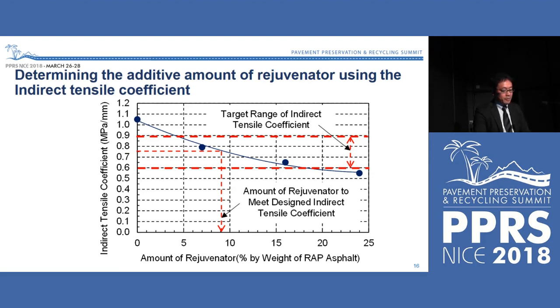This figure shows a way to determine the additive amount of rejuvenator using the indirect tensile coefficient. Using reference such as past records or optimal asphalt contents of virgin asphalt mixtures, the mixing ratio of RAP and combined grading are determined as well as provisional asphalt content. Specimens in which the additive amount of rejuvenator is changed are produced and the indirect tensile test is conducted. The relationship between the additive amount of rejuvenator and the indirect tensile coefficient is obtained. The additive amount of rejuvenator which gives the designed indirect tensile coefficient is determined. Afterwards, the Marshall stability test is conducted.